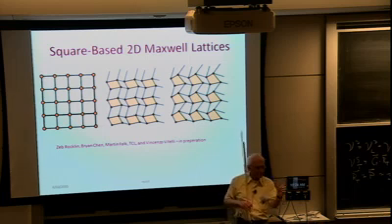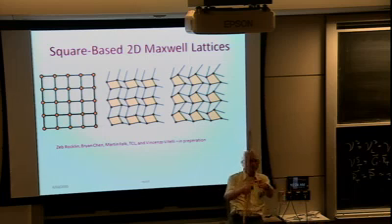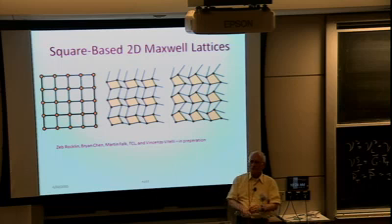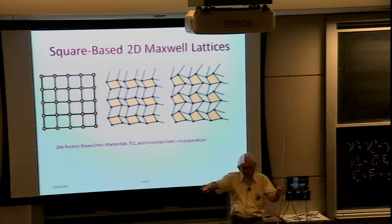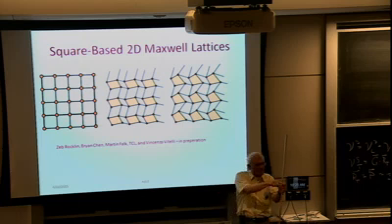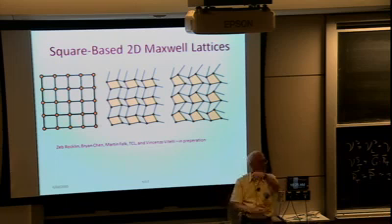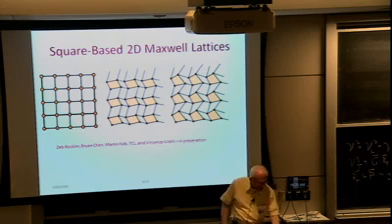There are Weyl points, and around them, if you do an integral in the complex plane, you get a non-vanishing winding number. So that means that the polarization is not uniquely defined. As you go along the surface, you can see that the number of modes as a function of the q vector along the surface changes, because you have these extra zeros, and that depends on the angle that I make the surface.